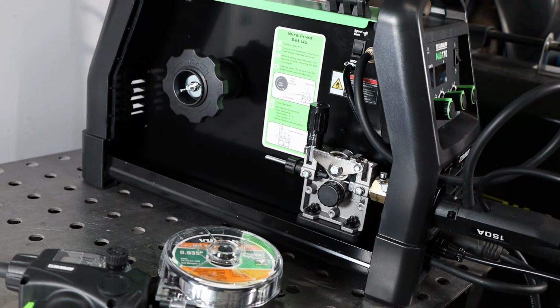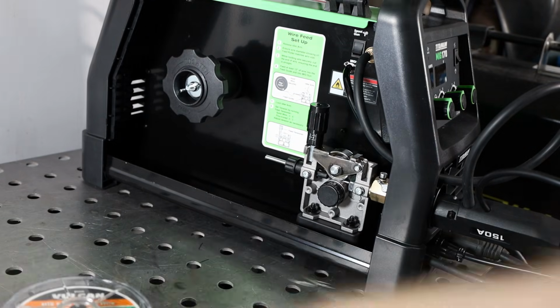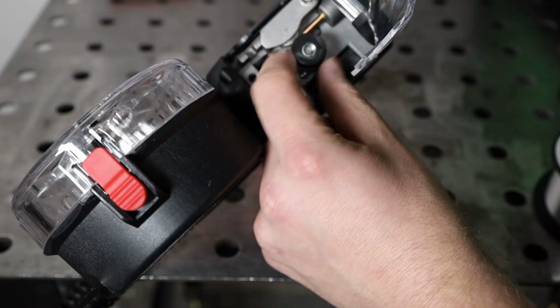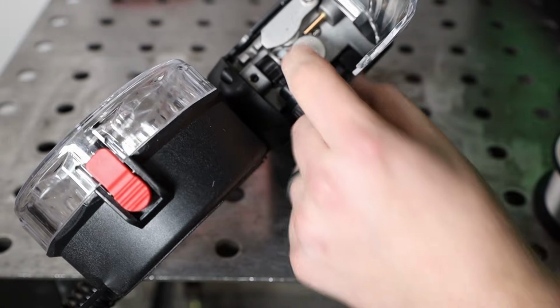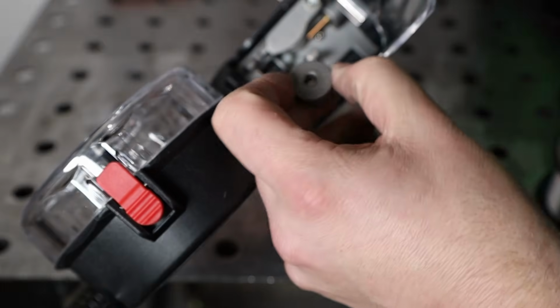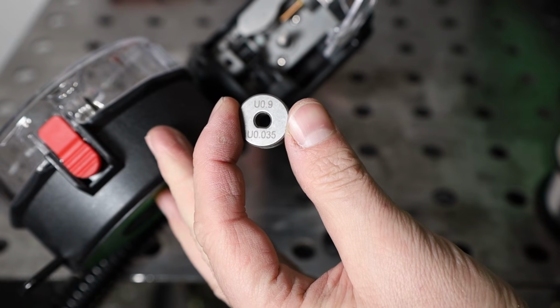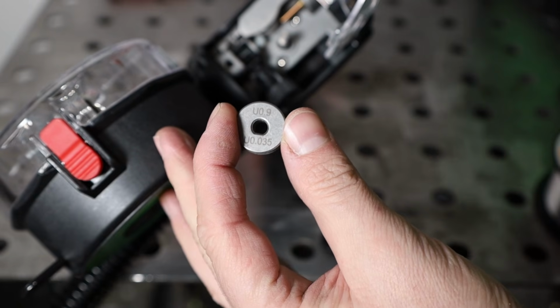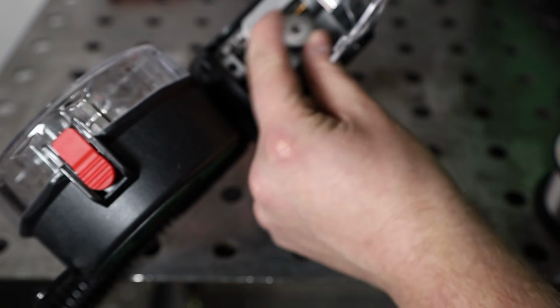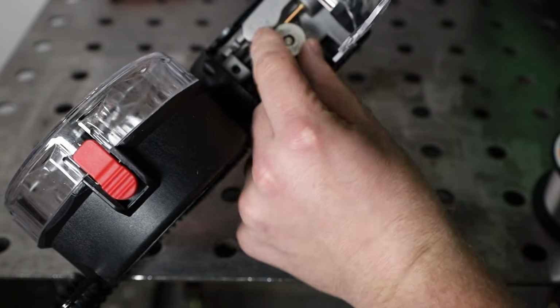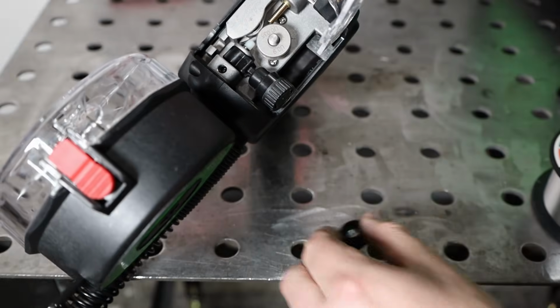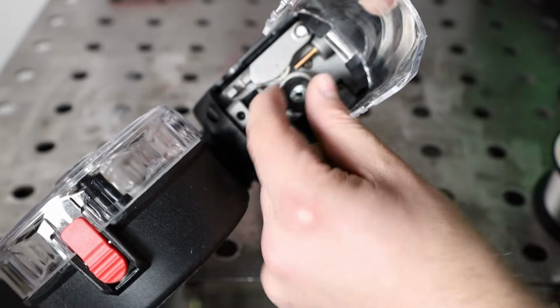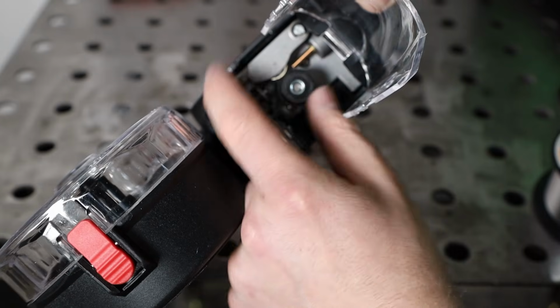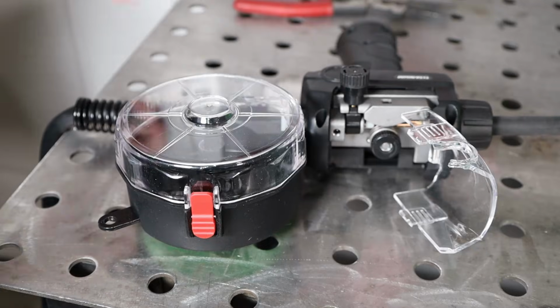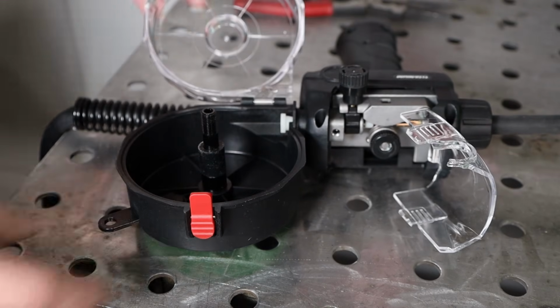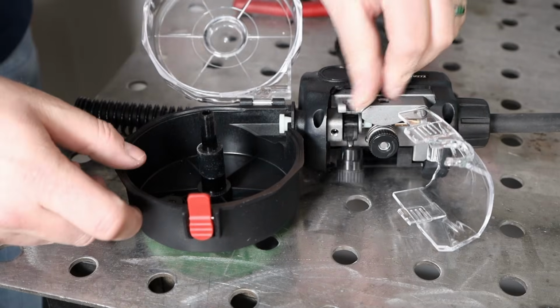Pretty simple. Then the connector hooks right in there at the bottom for your trigger and your feed motor, and you're ready to go. Now, before installing the wire, you just need to make sure that you're using the proper drive roll. See how it says 0.9 millimeters or 0.035, or 35 thousandths of an inch, and it has a U on it because this drive roll is a U-shaped roll, which is best for soft wires like aluminum. So you want that showing on the outside for whatever wire size you're going to load in. I'm going to be using a 35 thousandths of an inch or 0.9 millimeter wire here.